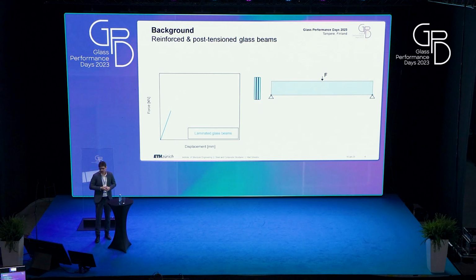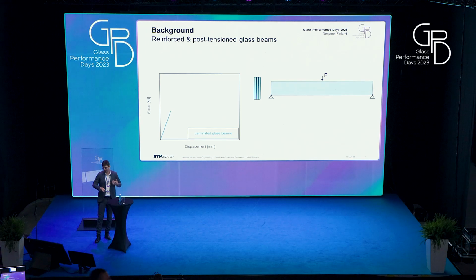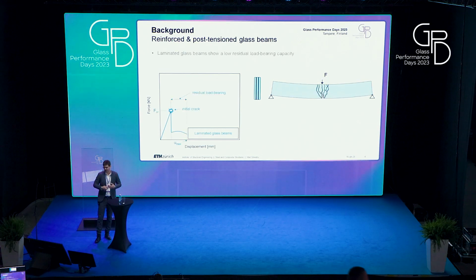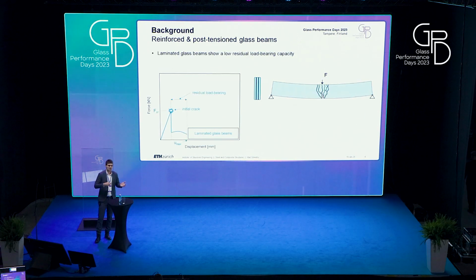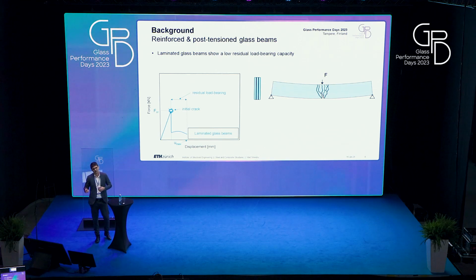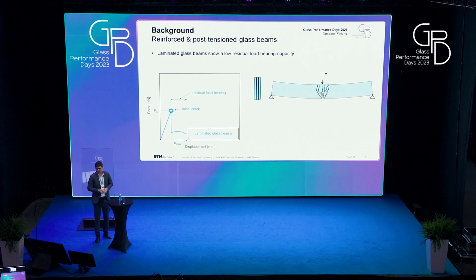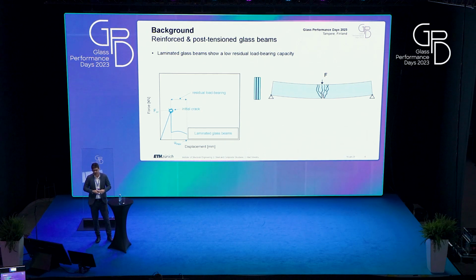However, if we look at the laminated cross-section of such a beam under bending, we will be able to carry load until we have a first crack. Afterwards, we have just a low residual load-bearing capacity, depending on the interlayer that is used. This is how it would look with annealed glass. With heat-strengthened glass, it looks similar. In our studies, we focused on annealed glass.